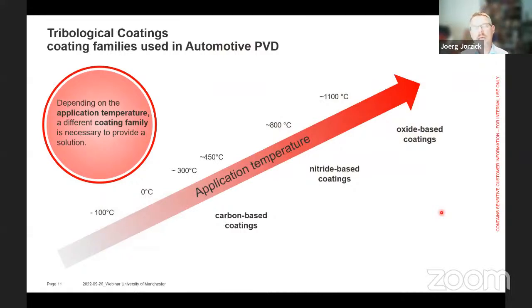One important temperature aspect when we talk about the coating solution with our customer is also the application temperature range. For different application temperatures, there are different types of coating families. It's not one dedicated coating, it's really a family. So for the low temperature coating area, we have the family of the carbon-based coatings, which are widely used for many, many applications. However, this only works up to 350, 300 degrees. Then we will have the graphitization of the diamond-like structure, and this does not allow the coating to survive this higher application temperature. So if we move above this temperature, we can choose from the family of the nitride-based coatings, which work pretty well up to 800, 850 degrees. And if the temperature is even above that, we can look at the oxide-based coatings.